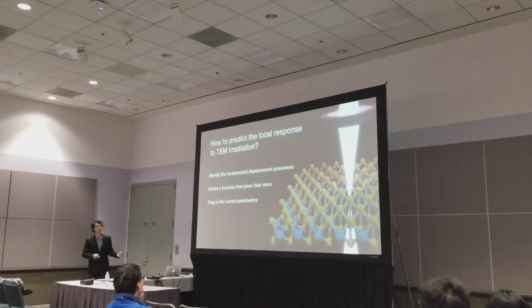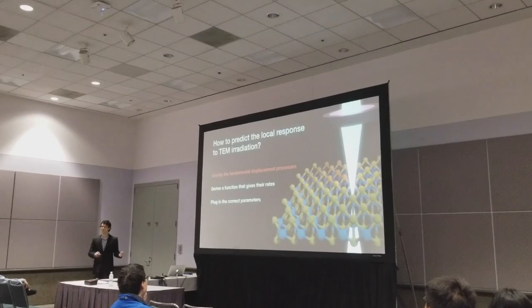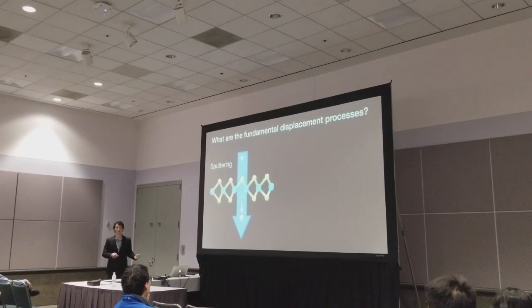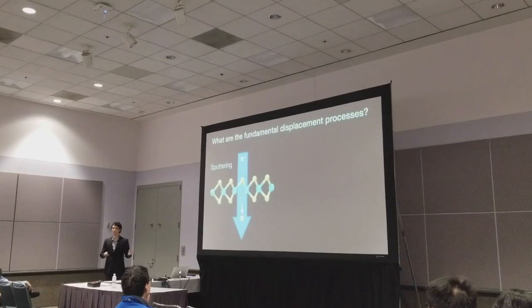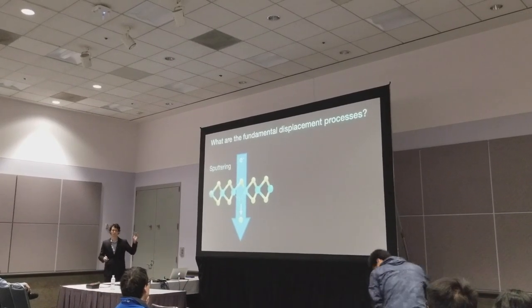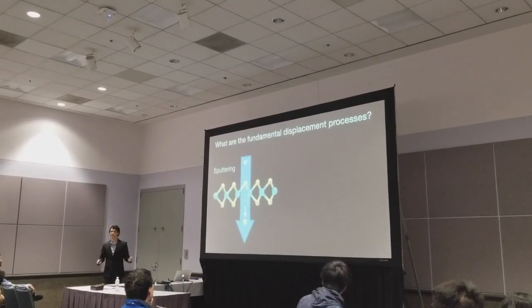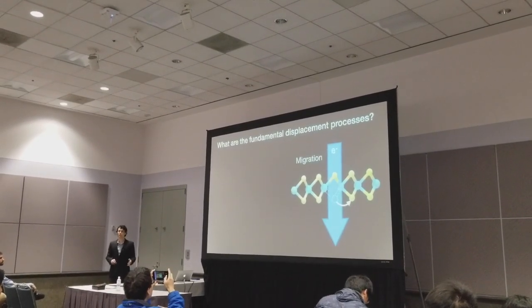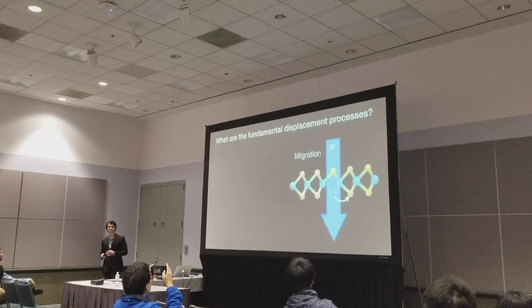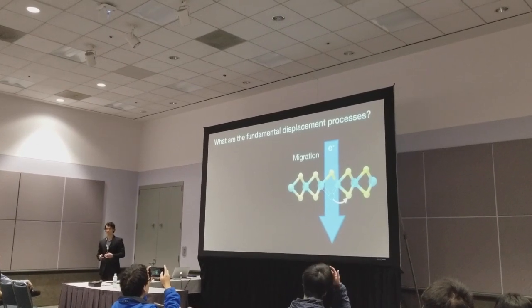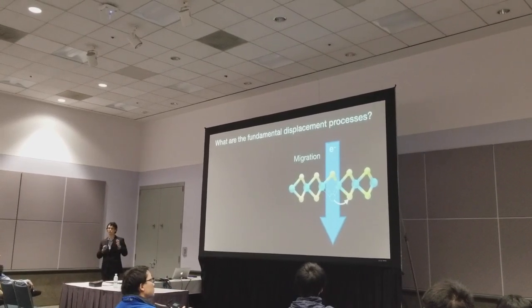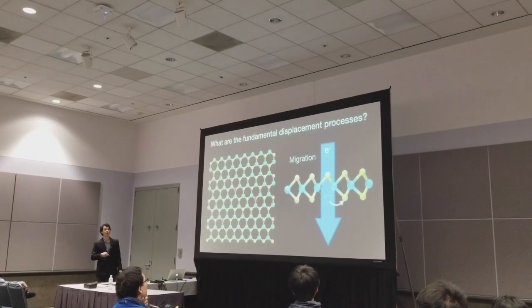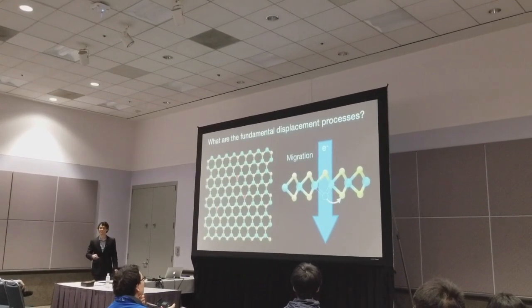It turns out that we can do quite a bit of engineering with a combination of just two displacement processes. The first, called sputtering, is the simplest. It occurs when an atom is knocked away from the crystal, leaving behind a vacancy. The second, called migration, happens when an atom is knocked into an adjacent vacancy, so that vacancy moves to where the atom used to be. In this way, vacancies can hop about the lattice from site to site.